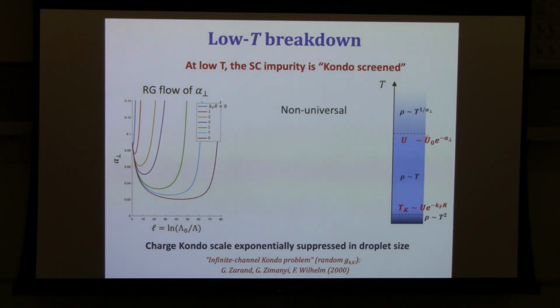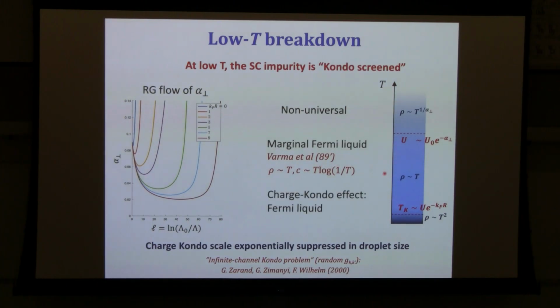Okay, at very high energies, there's a non-universal regime down to the renormalized charging energy, the typical charging energy of the superconducting puddle. Then we have this energy window between the charging energy and the charge Kondo temperature, where the resistivity is linear. This is actually a marginal Fermi liquid. We also predict that the specific heat should have this log T anomaly with a coefficient that depends continuously on doping. And ultimately, at the very lowest temperatures, we get the charge Kondo effect and we recover Fermi liquid theory.